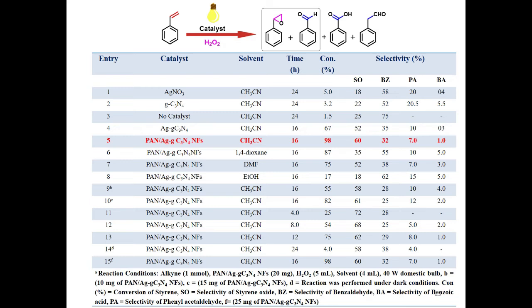If we look at the table, different catalysts were tested along with different solvent conditions and times. PAN/Ag-g-C3N4 nanofibers in the presence of CH3CN, methyl cyanide, proceed with the reaction in 16 hours, and the yield is 98%. Looking at the selectivity, styrene oxide gives 60% product as compared to benzaldehyde, phenylacetaldehyde, and benzoic acid. So it is more selective towards styrene oxide. This reaction is more selective towards styrene oxide in the presence of CH3CN as solvent and PAN/Ag-g-C3N4 nanofiber.